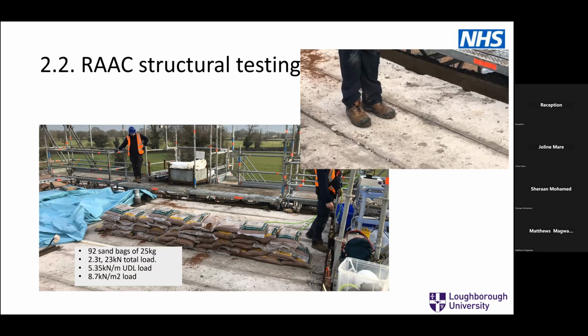So we had quite low hopes of it taking much load, and partly because of the collapses we'd seen. But when we did load it, you'll see there, 92 bags of sand. The engineers amongst you, a very decent UDL load and a very decent load per meter squared, as in 2 or 3 times the design load. So it took 2 or 3 times the load it was designed to. So if you do it properly, this material is strong and takes a great load.